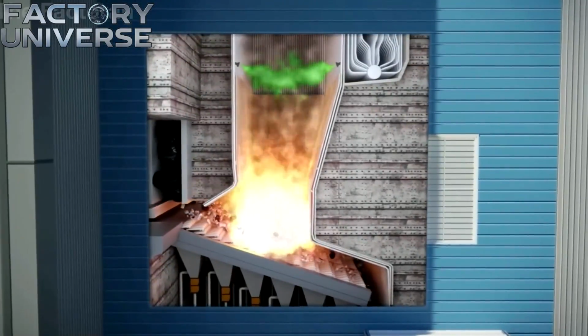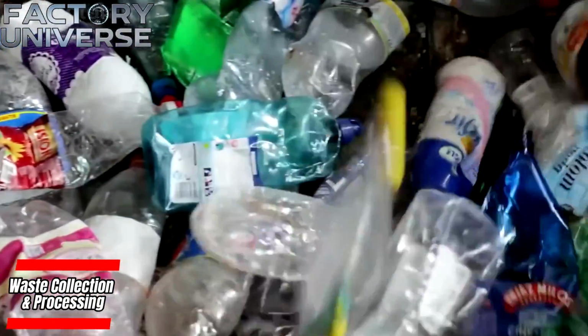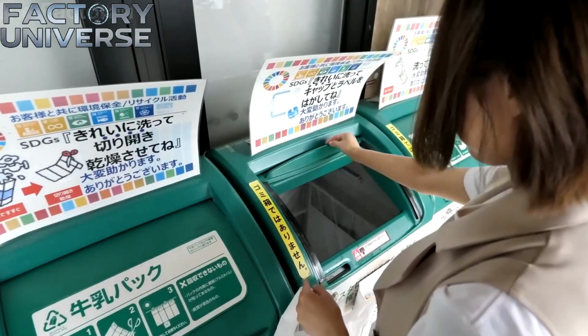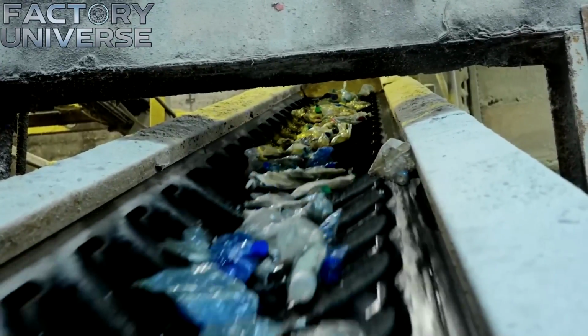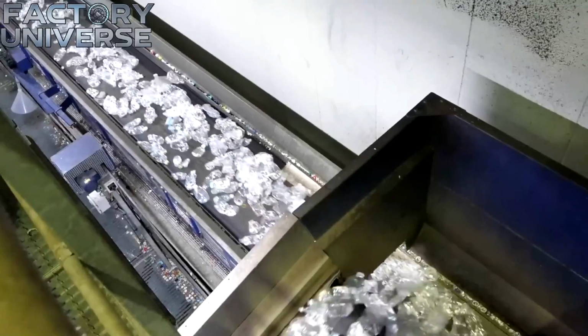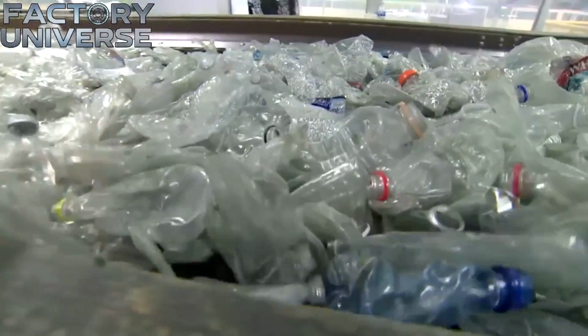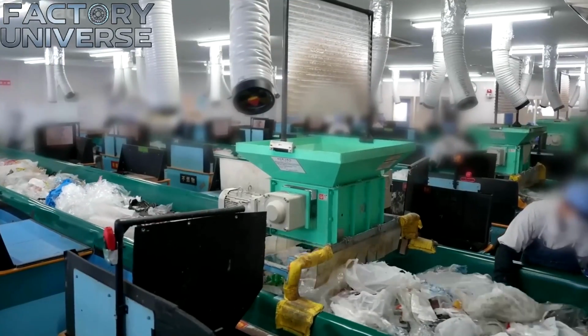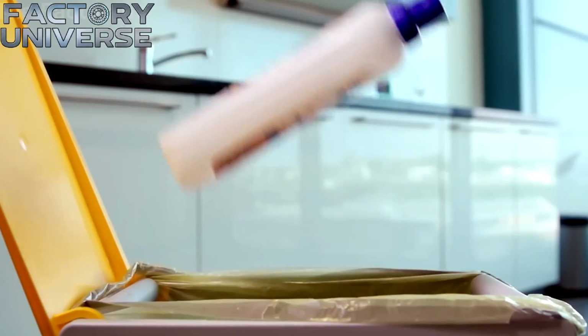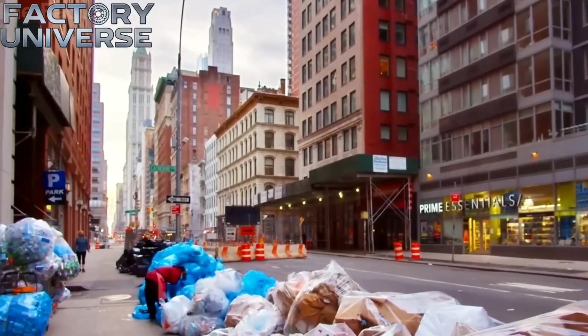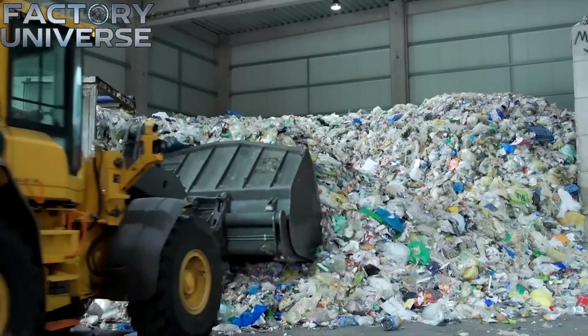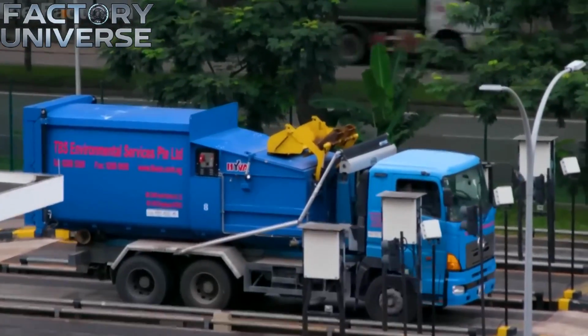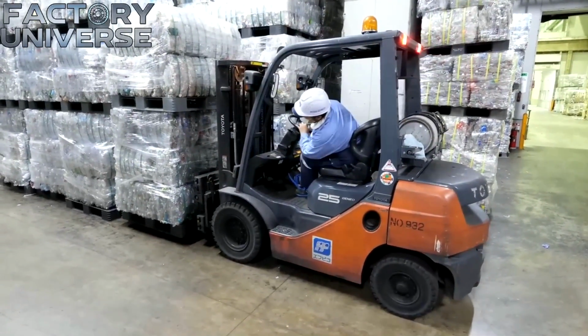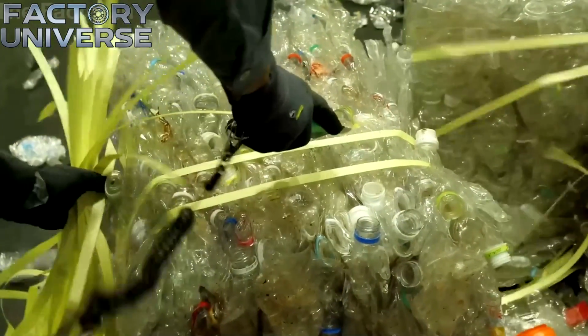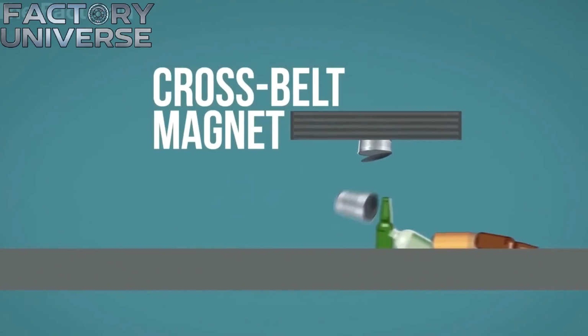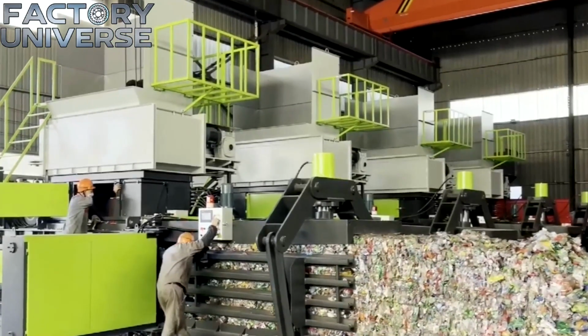The hydraulic press chamber resolves this by using steel pistons to generate thousands of pounds of pressure against the material. No heat is applied during this compression, yet the volume of the plastic is reduced to a small fraction of its original size. After several tens of seconds of intense mechanical force, a solid plastic bale is ejected from the machine. These blocks can weigh from several hundred pounds to more than 1 short ton, depending on the specific industrial plant design. Soft films and rigid plastics are now locked into a single standardized unit. This makes handling by forklifts significantly faster and safer, ensuring the facility operates with maximum efficiency.